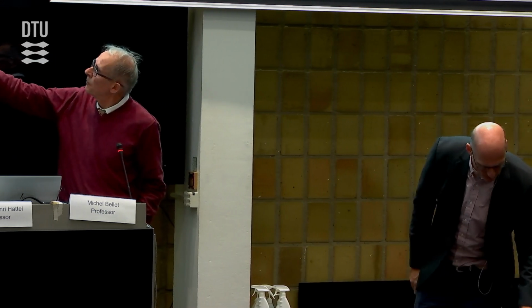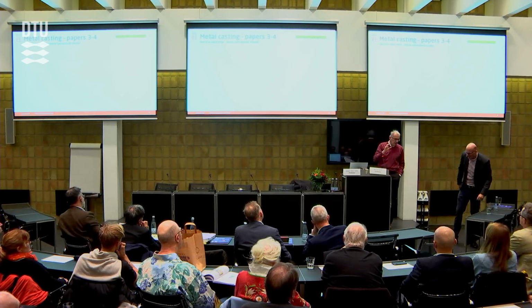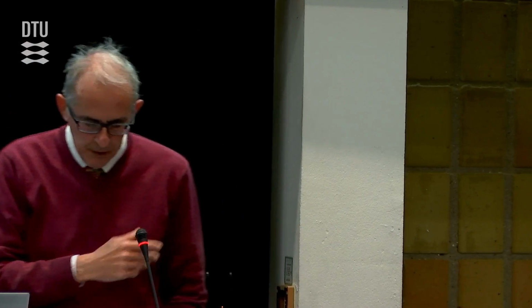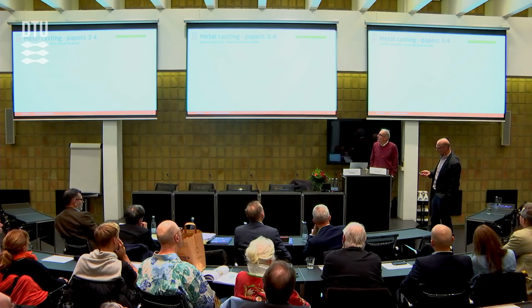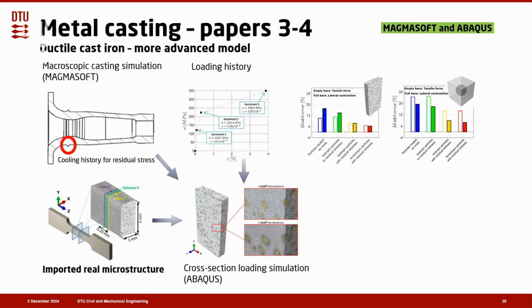That's also coherent due to the fact that we can see the mesh. But the finite element mesh is not so fine to be able to describe reliably the surface region of the nodule. No, the mesh is not so fine. So probably this is consistent with what you said. Yes, I think you're right. The mesh is refined, but not so much in this periphery. As you see, there are only 5 million elements. Only 5 million. And it actually calls for a lot more if we should do the resolution that you say.